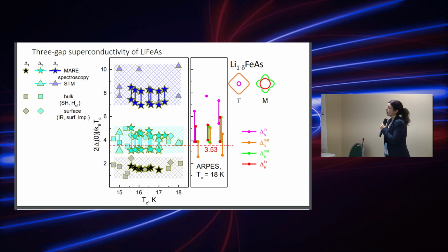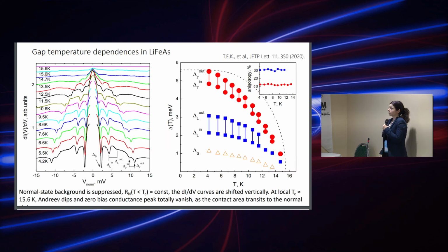of the literature data. All these 2 delta on kTC ratios keep almost constant with critical temperature, so all gap energy parameters scale with critical temperature TC in the studied TC range. Now let's check the temperature evolution of the determined energy characteristics.